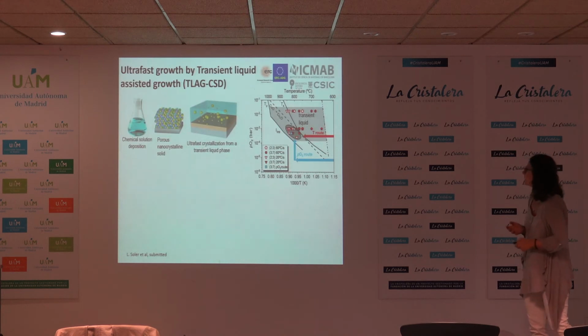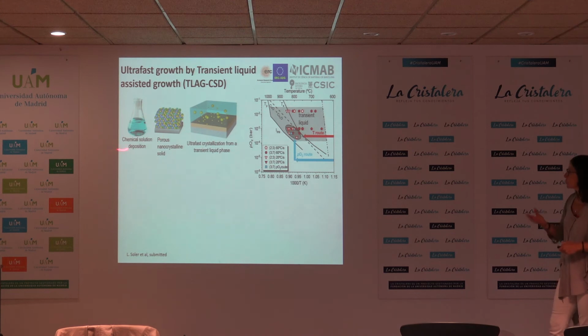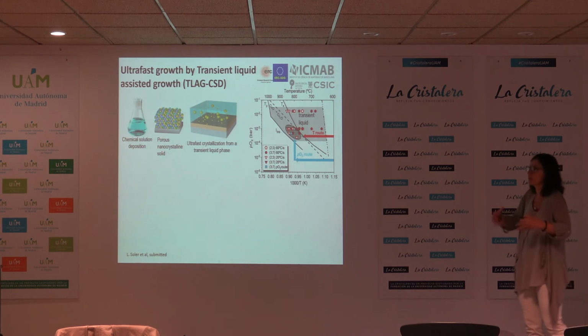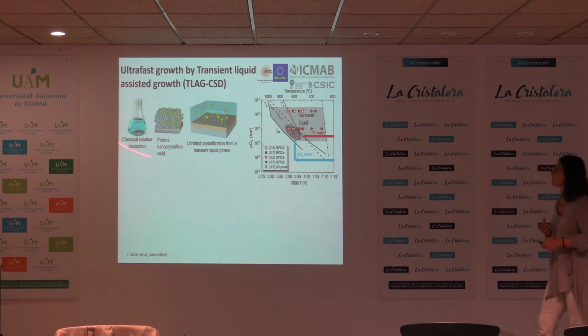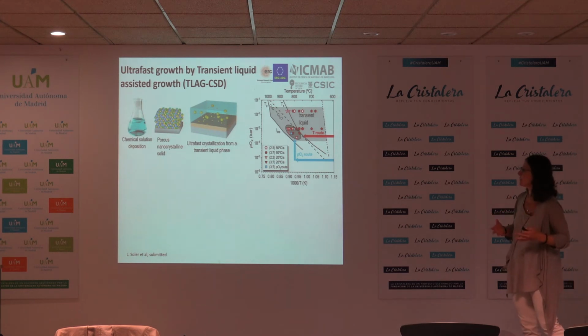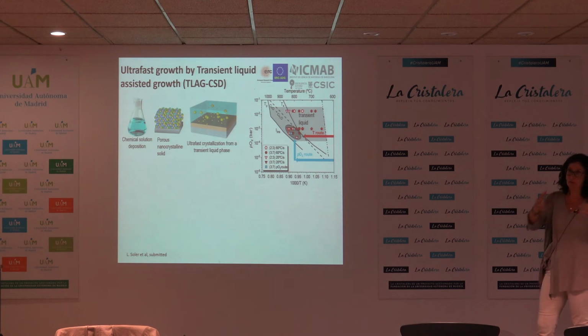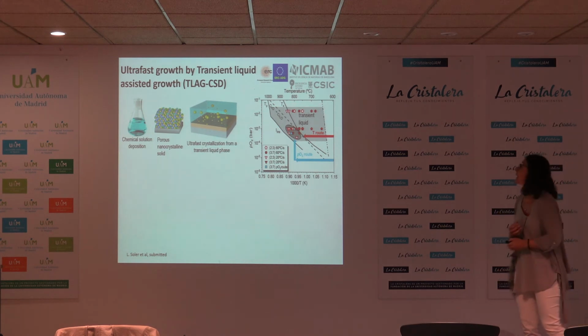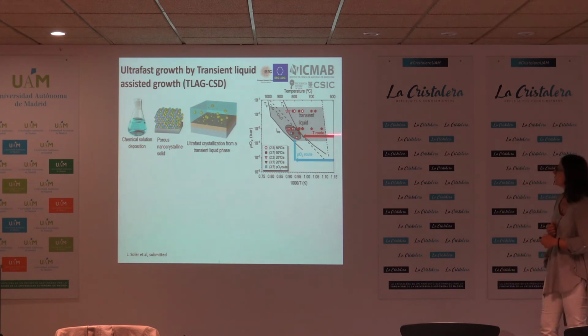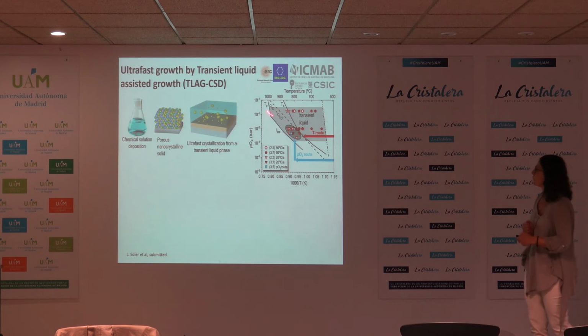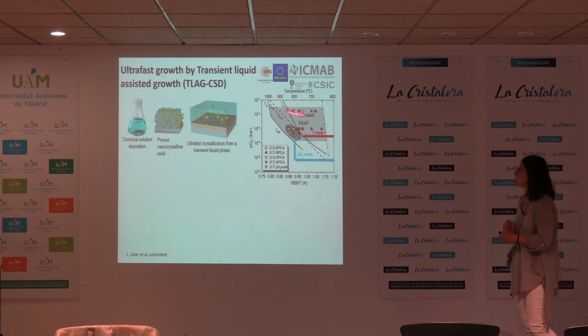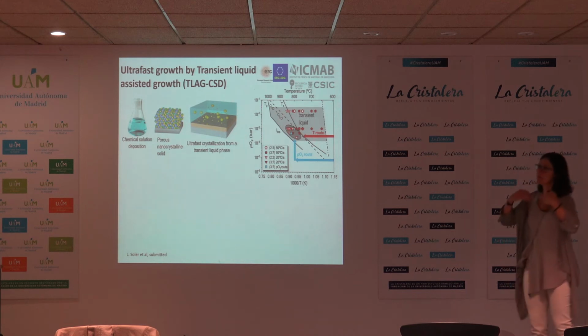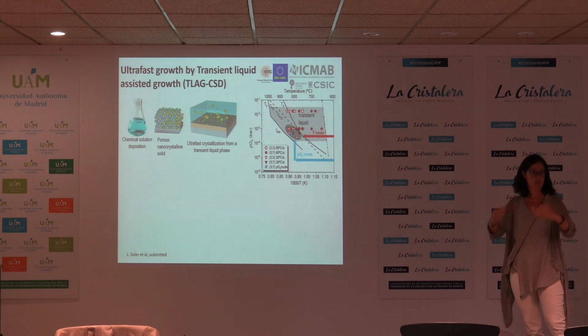So, in fact, the idea here is that we will have a solution. Now, the initial precursors will be different. We will have the same pyrolysis. We end up with nanoparticles. Now, we will have one of the nanoparticles which will be barium carbonate. And then we will go to this region of the phase diagram where the YBCO can grow. But we will do it in a way that we will be able to first form a liquid of barium copper before the YBCO can grow.